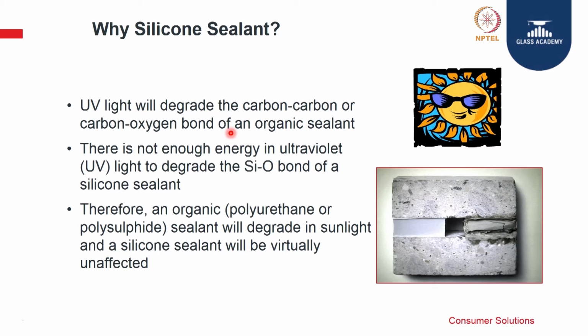You do not do that in buildings, because what you use is silicone, which cannot be degraded by the UV in the sunlight, because the bond energy of silicone oxygen is much higher than the UV in the sunlight energy. If you look at this picture, the left side is silicone and the right side is polyurethane. When it was subjected to a simple accelerated UV test, the PU completely got degraded in hardly 2500 hours. This is like 3 or 5 years of life, whereas the silicone did not get degraded at all.